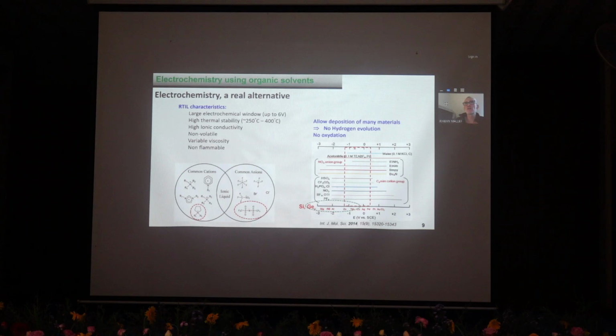And then if we compare, on this diagram, this square here is the electrochemical window of water. We see that we are limited in the number of materials that we can deposit in water. Let's say copper, for instance, we can deposit copper, reduce copper ions, or strip copper. But we are limited. Here we see all of those different organic solvents. If you use a good combination between the cation and anion, you can have an electrochemical window of up to 6 volts, giving us then the possibility of growing silicon, germanium, for instance, different rare earths, aluminum, etc.